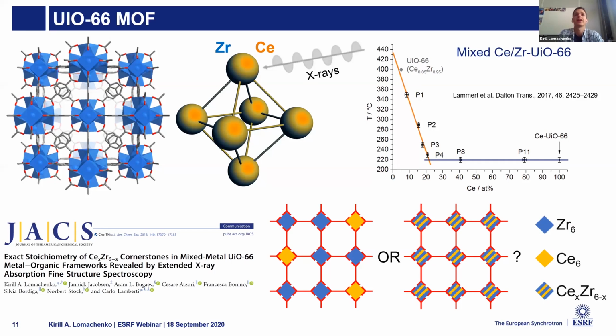EXAFS was particularly helpful because with zirconium K-edge and cerium K-edge EXAFS, you are very sensitive to this metal-metal interaction. So you can determine the metal-metal distances and distinguish easily between cerium and zirconium neighbors.